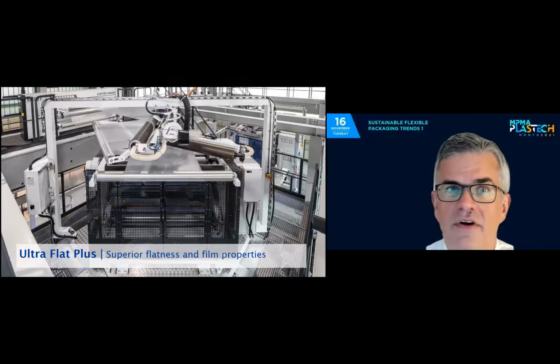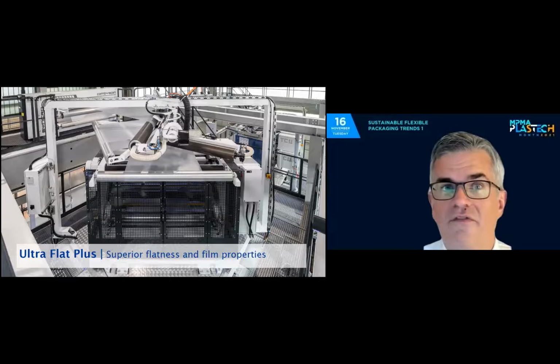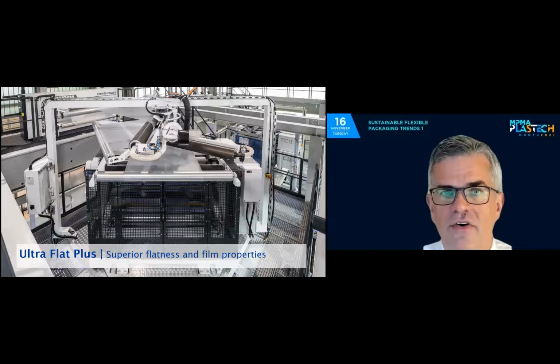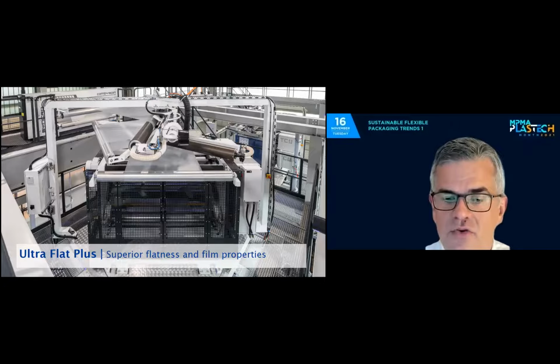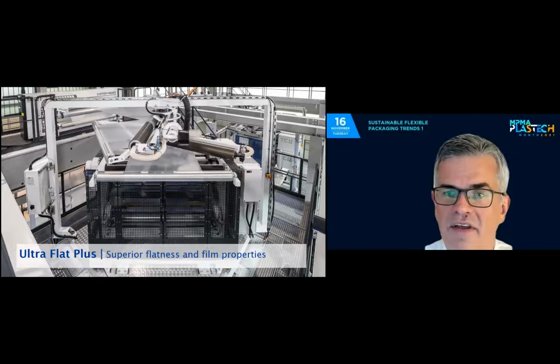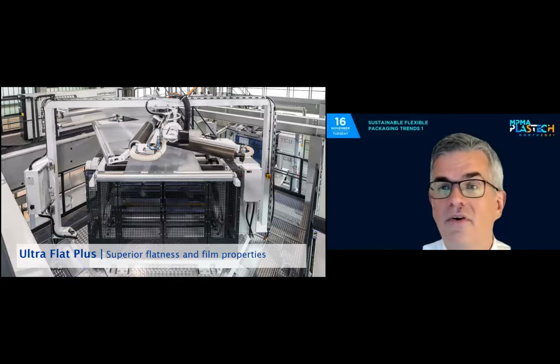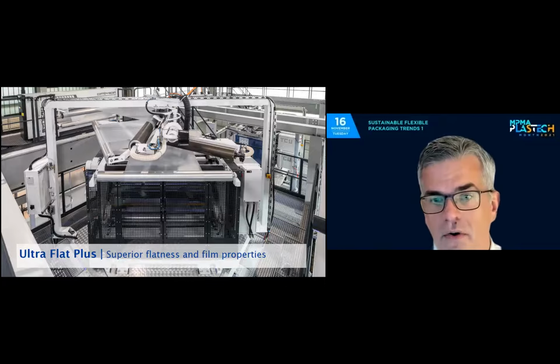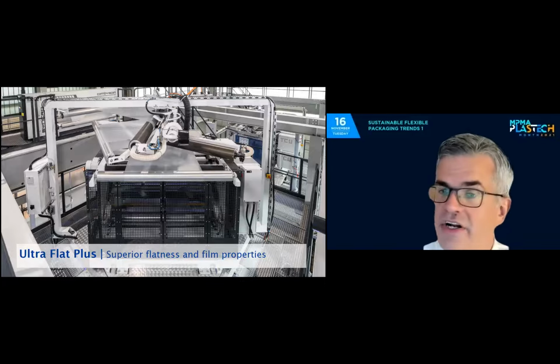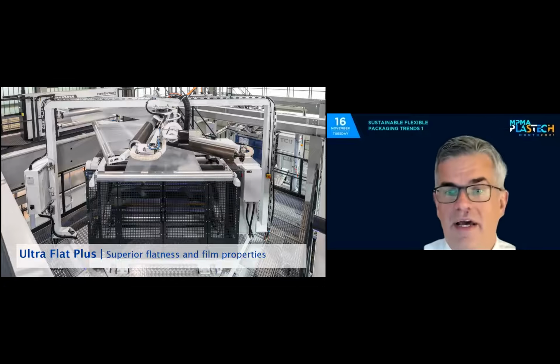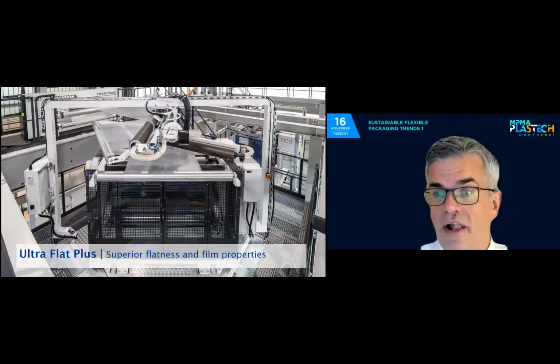So if I talk now about stretching, I don't talk about 300, 400 or more percent of stretch. I talk about a stretch rate between 70 and 100% to improve properties of biopolymers, giving them a little bit better appearance and a little bit better mechanical properties. And the tool for doing so is, again, a stretching unit positioned on top of the line. But in this case, we do not need so many rollers like we need in an MDO to stretch 500 or more percent. This was like 10 or 12 rollers.